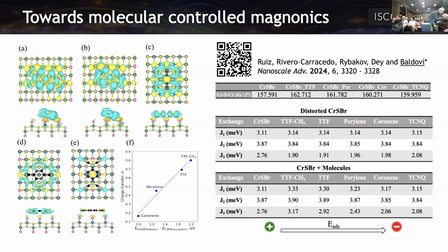Yeah, for example, in the case of the magnon gap for the topological magnons, we are having double the effect of the calculation. So it's a factor of 2, but for a very, very teeny region, like we are talking about 1.3 meV versus 0.7 meV. In the case of the exchange interaction, it depends a lot on how we tune the Hubbard-U. That's one thing. No? For example, we are fitting the magnon dispersion of the chromium sulfur bromide, and then for a Hubbard-U around 3, we can get a very good description. We are very close, and the Curie temperature, we are predicting 122 instead of 146. So for this, because our calculation is always based on an ideal model of a perfect 2D material. We don't have the substrate and all these effects.